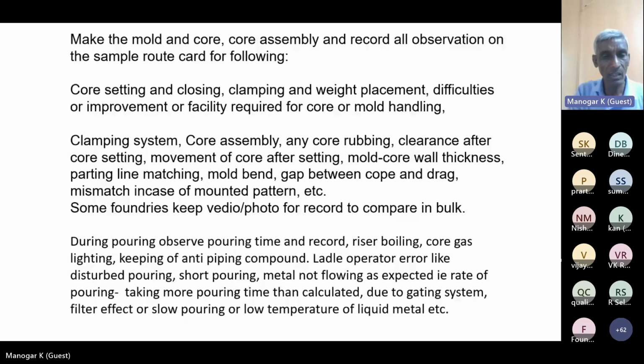And pouring time is an important thing, whether as per the calculated pouring time, it has been poured or not. If there is any difficulty or any disturbance while pouring, the person should record all that, so that based on the casting result, we can correlate the reason for the defects.